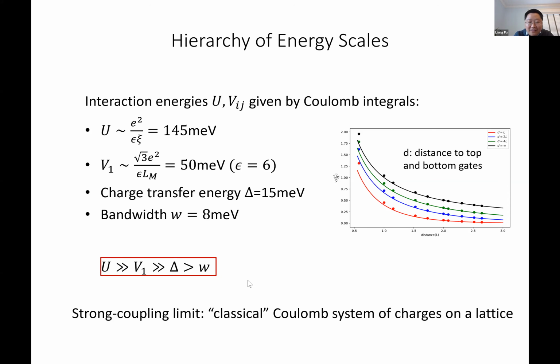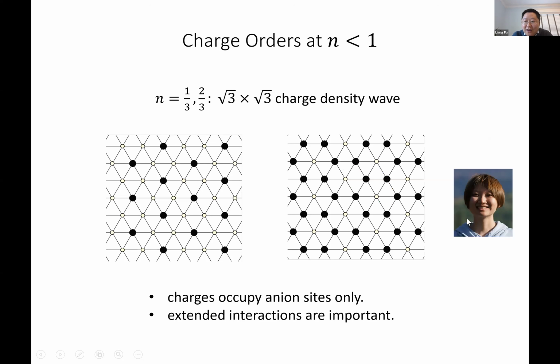And it turned out, just to show that in this picture, it becomes immediately clear why these charge order states appear at fractional filling. So again, you take this classical limit, turning off the hopping between sites. This is a Monte Carlo simulation in this classical limit by Tongtong Liu. And you see that at 1/3 and 2/3 filling, the electrostatic repulsion energy is minimized when charges form these density waves, which enlarge the unit cell by a factor of 3.